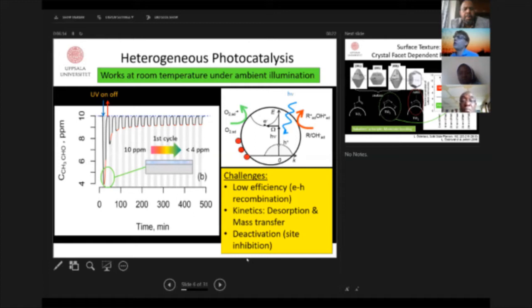Here's an example. This is actually gas phase, which you see in the third picture from the left. You flow gas, acetaldehyde is shown here. You can see initially we have a huge drop of the pollutant concentration, as you want, and then it gradually increases. This is a deactivation process. Something happens, and this is usually when you have a surface and it occurs at low temperature, that you're typically kinetically limited by desorption or even deposition of some strongly bonded intermediates. So you actually populate sites and eventually become covered, and it doesn't function as well as it did initially.